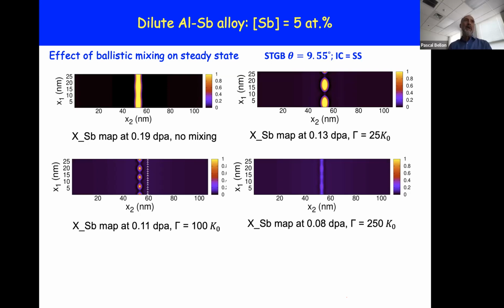Yeah, that's a very good point. Originally, when we studied alloys under radiation and then alloys under severe plastic deformation, we saw those two situations as two different examples of driven or non-equilibrium systems, but two very distinct examples. The physical processes are very different. The way irradiation creates damage in an irradiated material is very different from the way dislocations may modify the microstructure of an alloy. So we were in fact surprised when we saw that, say, in copper silver and copper niobium, you tend to see almost the same or very similar microstructures in both environments. This being said, we don't necessarily have a good way to fully capture these similarities.